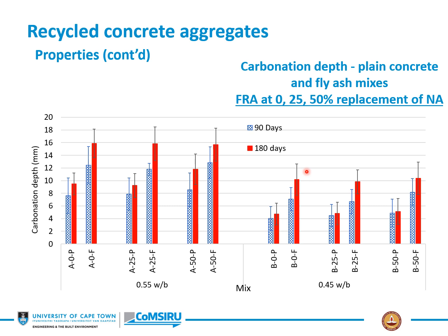Here is something on carbonation depth and 2 different water binder ratios. And obviously it's as you would expect, the lower water binder ratio giving you the lower values. And again, the carbonation depths are not adversely affected at these different ages by the use of, in this case, fine recycled aggregate at up to 50% replacement.